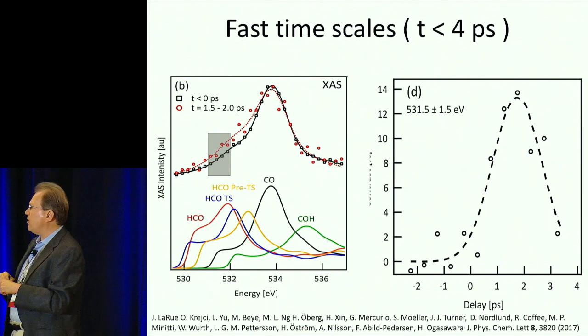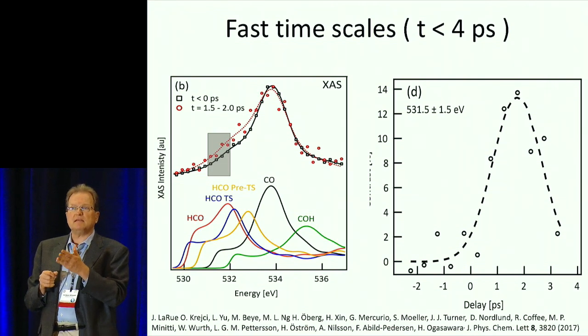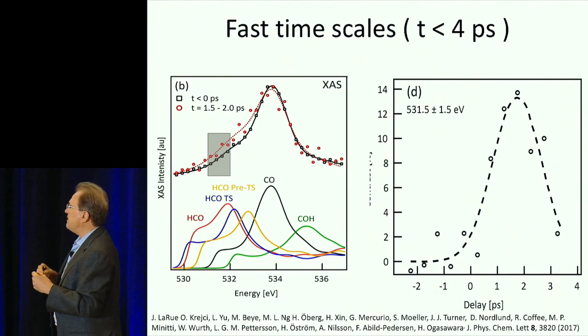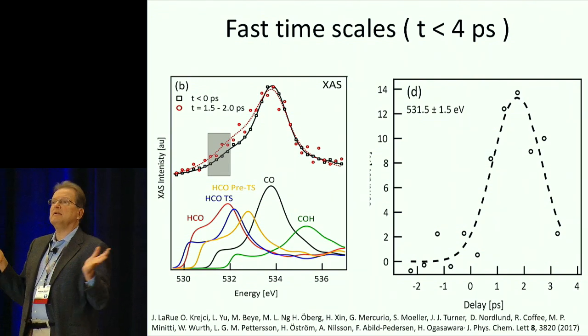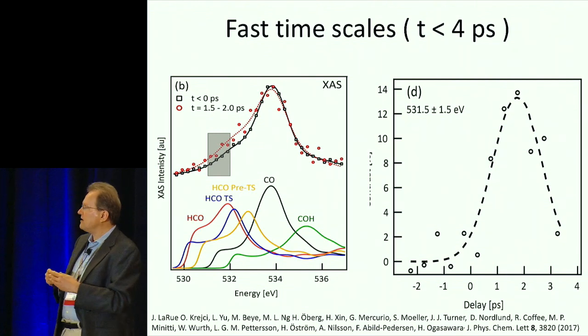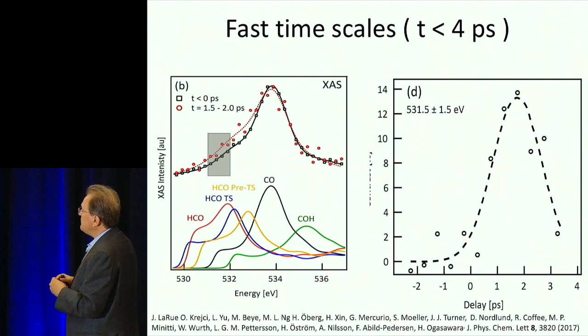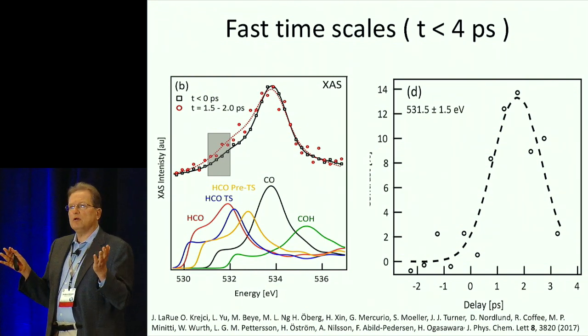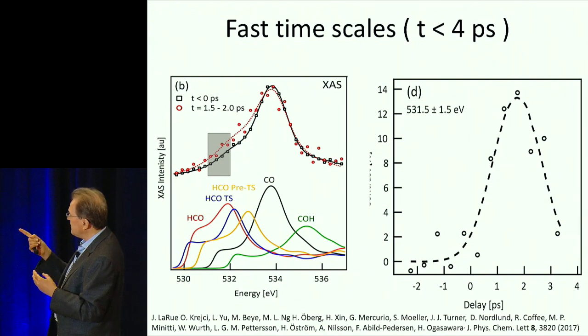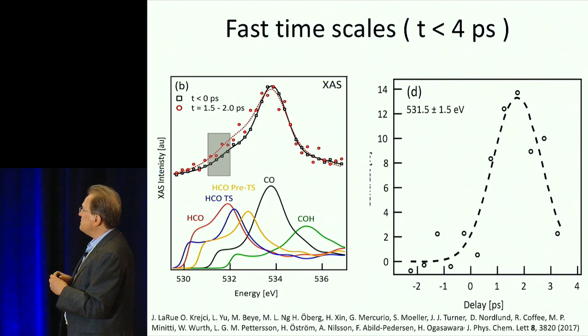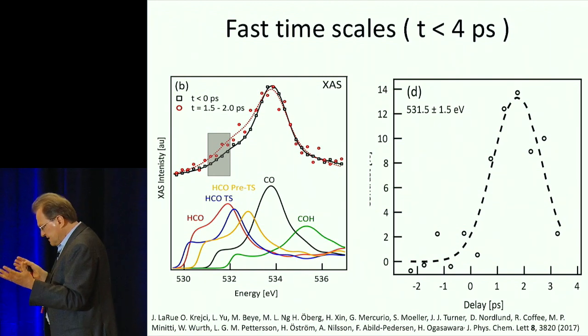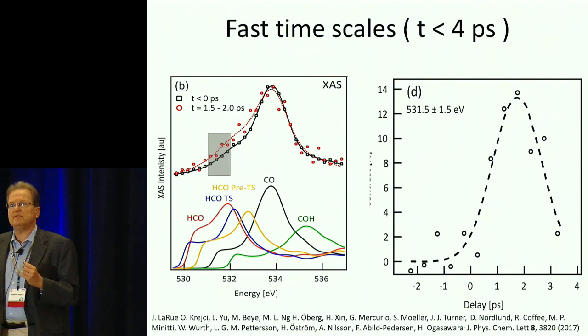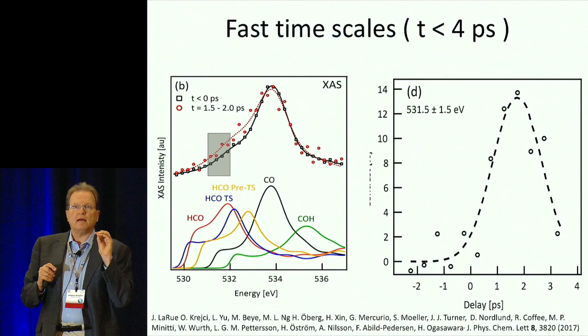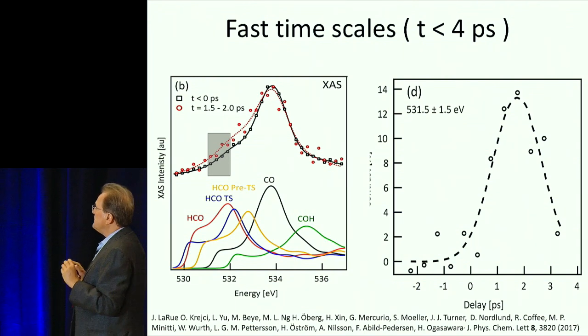If you add the hydrogen on the oxygen side, we should see a shift of intensity to higher energy, which is the green there in the calculated spectrum, and we clearly don't see that. If we instead attach the hydrogen to the carbon side, we can have different types of species there. We can have the more stable HCO, which is the red one, and then we can have something close to the transition state or on its way to the transition state, and you can see a number of spectra. Well, clearly, we are seeing a distribution of these coming up, and this directly tells us we are seeing the HCO species, and the hydrogen is attached to carbon, and there are a number of distributions.